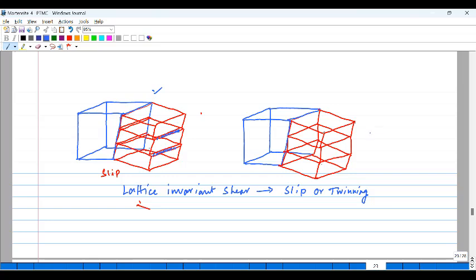And in this one here, twinning has taken place for the shape recovery. So you can see this twin here, for example, through which the shape has recovered to the observed macroscopic shape of Martensite. So a consequence of this is that the habit plane indices are not rational, because the amount of lattice invariant shear which is needed to recover the macroscopic shape is in itself not rational.